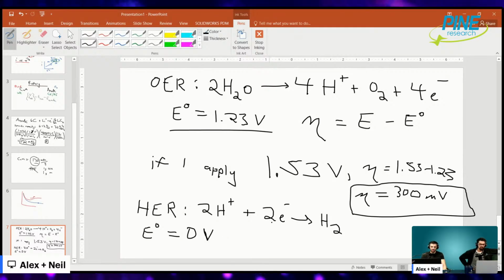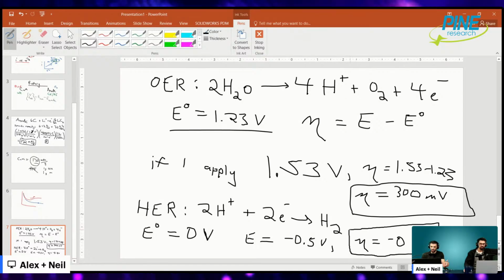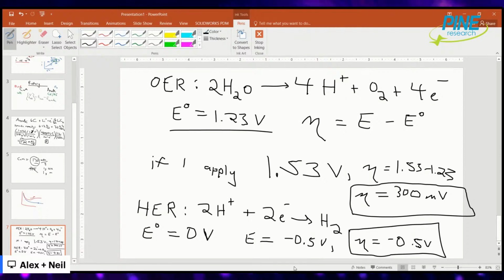And so the same thing applies, right? Because it's a reduction reaction, we would want to go negative. We would want to apply a negative overpotential. So if we apply E equal to minus 0.5 volts, you could see this either way. Sometimes you'll say overpotential is minus 0.5 volts, or you'd say your overpotential is 500. They might neglect the minus sign. It's sort of implied. It depends on where you read. Sometimes people will just say 500 millivolts of overpotential, but if it's a reduction reaction, it's going in the negative direction. But technically speaking, the correct way is to say it's minus 500 millivolts or minus 0.5 volts of overpotential. So again, it's just how far away from the standard or from the thermodynamic potential you are, which is a way of saying how much you're driving the reaction, so to speak. Because kinetically, your current will be proportionate to your overpotential.